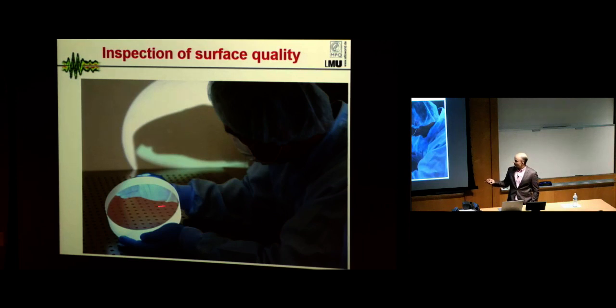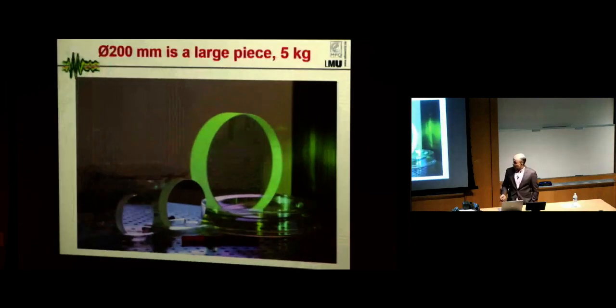Here, for example, is a mirror, because when we produce a mirror and want to use it for high energy applications, the layers which we produce should not include any defects. It means all this production is done in a very high class clean room, and of course this mirror should not be touched by any means, and the substrate should be prepared in a very special way, and so on.